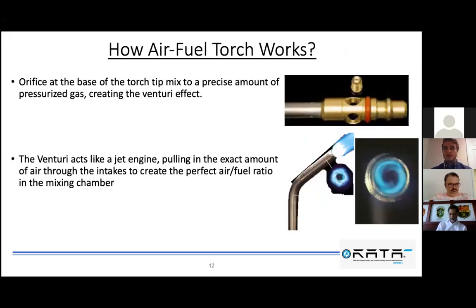Perfect. So we can see that there is a wide difference between oxyfuel and air fuel, and this comes from the source of oxygen. And how does the air fuel torch work? The picture on the right, the top picture, is the bottom of an air fuel tip. An air fuel tip will always have an open orifice, more than one, which will allow it to create a venturi effect. This venturi effect, with the pressure from the fuel gas that is coming in, will kind of suck the air that it has around it and provide the perfect combustion between oxygen and fuel. So then you'll be able to have a flame.